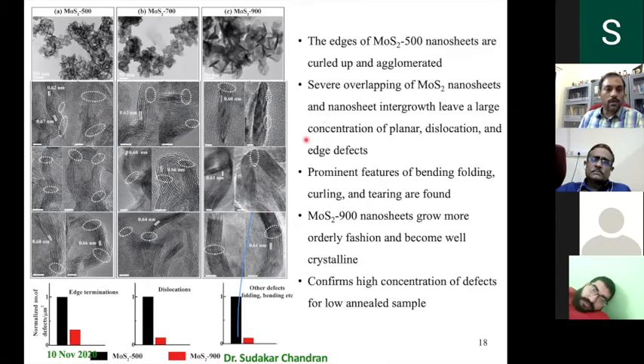Okay, so to give a little insight on what these defects are and how you see there are defects, here I have put a collage where MoS2 prepared at 500 degrees Celsius, 700 and 900 are shown. As you can see, there are a lot of wrinkles. Just look at this low mag image. Very immediately you can find out the crystals in the 900 are kind of flat, straight, whereas in the 500, a lot of wrinkles are there. They are much smaller, and that is kind of in between in the 700 degrees Celsius annealed sample. So pretty much you can get convinced easily that by careful annealing and the number of hours you anneal at a given temperature, you can get rid of these defects.